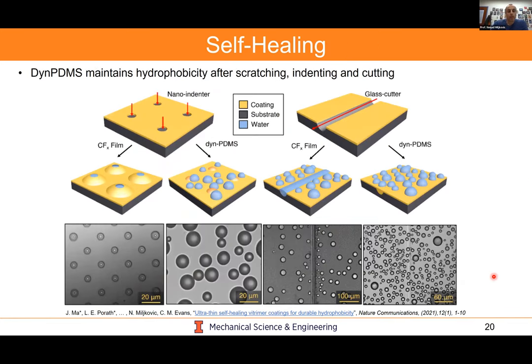The student then went on and did a lot of very interesting work using the nano indenter to put pinholes. You can see here, these are pinholes that form on a conventional surface. If we place these same pinholes on our self-healing surface, we don't see anything happen because of the self-healing. If we were to do mechanical scratches, like physical, hundreds of micron scale scratches, you could see the same thing. The coating will self-heal. You'll have nice uniform dropwise condensation after you condense on the surface itself, right? After it self heals, it basically doesn't see the scratch at all here, whereas the coating without the self-healing, you'll see a very thin film form within the scratch and no droplets are formed within here.